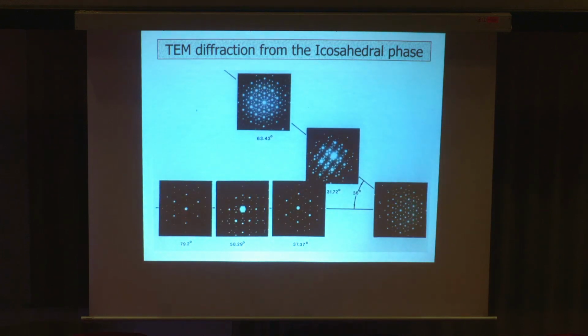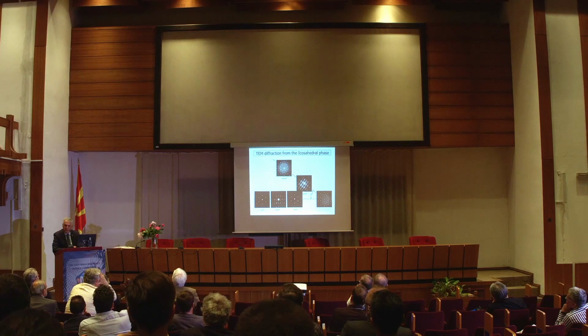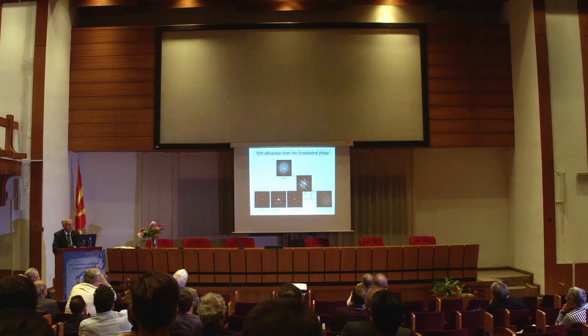So, that diffraction pattern was one of many. Of course, in the electron microscope, you can rotate a specimen and you can tilt it, so you can bring it by the goniometer into different positions. And this is a series of diffraction patterns. On the lower right, you see 5-fold rotational symmetry. As you go up, you see 5, 2, 5 again, and down there you see 5, 3, 2, 3. 2 and 3 are allowed, 5-fold is not allowed in periodic structures. This set of diffraction patterns has an icosahedral symmetry, and I will explain what it is. Just if you look at the angles, you see the angles are marked down there.